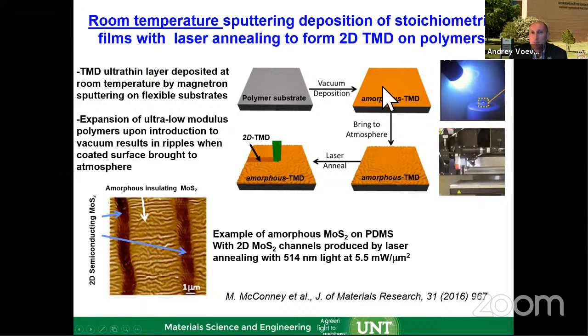You produce an amorphous film by PVD methods at room temperature on any polymer substrate, and then bring in lasers to anneal. During annealing, depositing the energy on that very thin amorphous material converts it to crystalline 2D material where you put the energy of the laser. That leads to direct writing of hexagonal crystalline material on amorphous material. From a physical properties perspective, the amorphous material is insulating, and the crystalline is a semiconducting material. So essentially you can write semiconductor channels within the insulator. And this leads to device fabrication in a direct way.